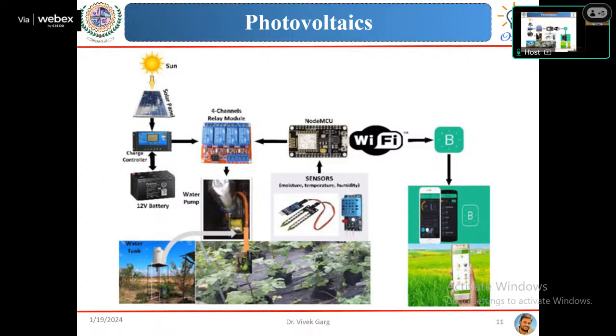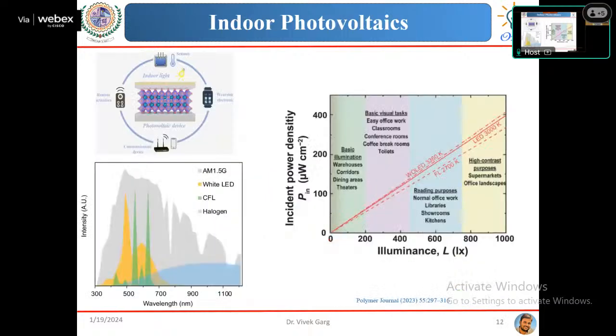So this is a scenario in the case of outdoor photovoltaic devices, but we are mainly concerned about indoor photovoltaic devices in this session. In the traditional outdoor photovoltaic devices, the material requirement is totally different. The reason for that is, you can see in this plot, the solar spectrum received at the Earth's surface is this gray one, and this intensity is widespread up to 2000 nanometers. That is shown up to 1100 nanometers, right? If you want to utilize this energy, your band gap should be at this edge. If the energy is higher than this edge, it will be absorbed by that material.